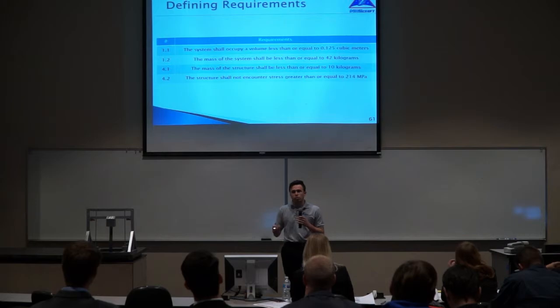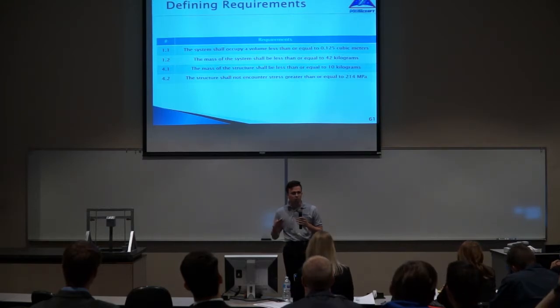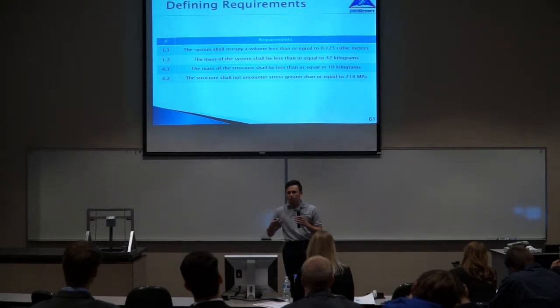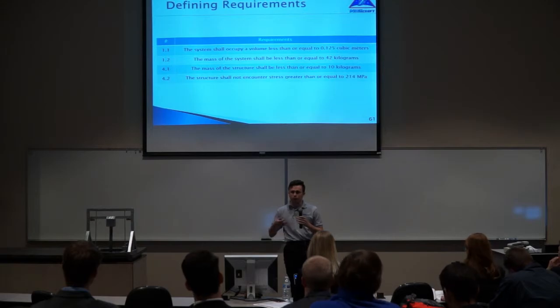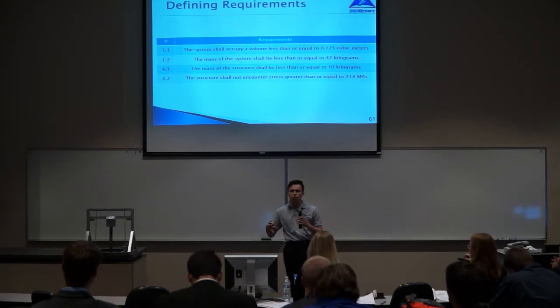Second, the structure shall not encounter a stress greater than 214 megapascals. This is the ultimate yield strength of aluminum. This was a very conservative force applied to it, so that if we encountered any forces that could break aluminum, obviously we're in trouble, and it would allow us to resort to stronger materials in case of that failure.